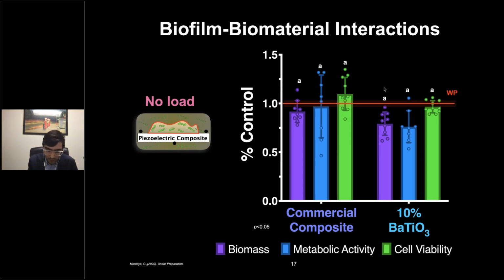The first thing we measured again was the biomass - this is the first bar plot. The second thing was the MTT metabolic activity, the second bar, and the third evaluation was cell viability, or CFU. We normalized all responses by the well plate, which served as our control. Every time we ran the experiment, we grew the biofilm on the well plate and normalized all our results based on that, which is why everything is normalized to 1.